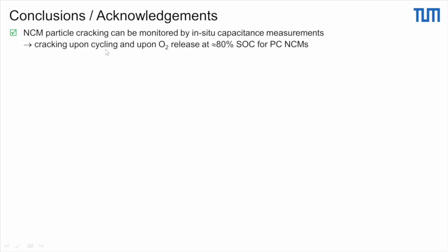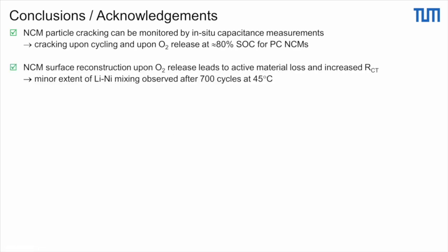And what we see, of course, is that it increases with cycling and upon oxygen release at about 80% SOC, but that only happens for polycrystalline materials and not for single crystals, reinforcing this assumption that the weakest point is really between the single crystallites in a primary, in a secondary agglomerate. The other thing is we see a surface reconstruction upon oxygen release, which leads to an active material loss and an increased charge transfer resistance.